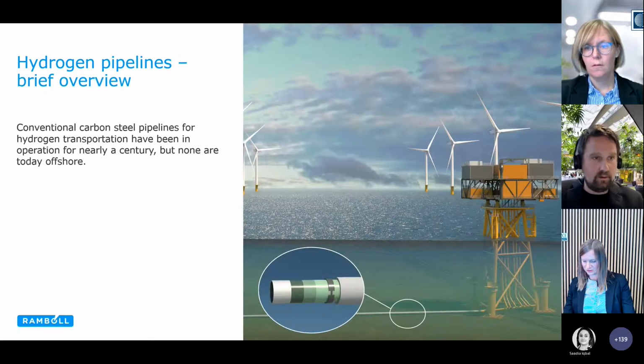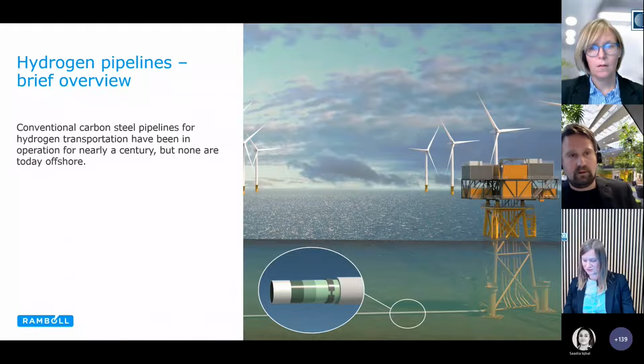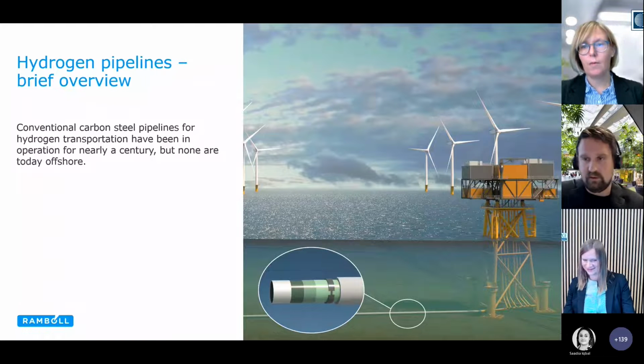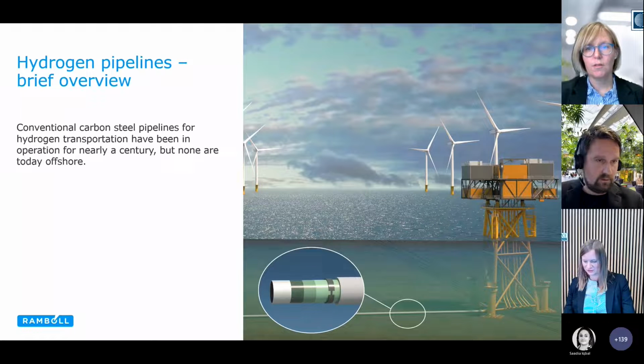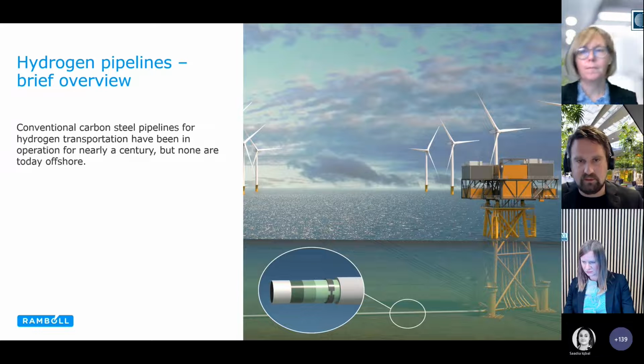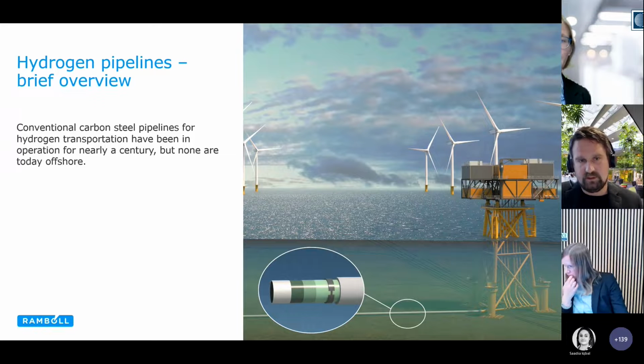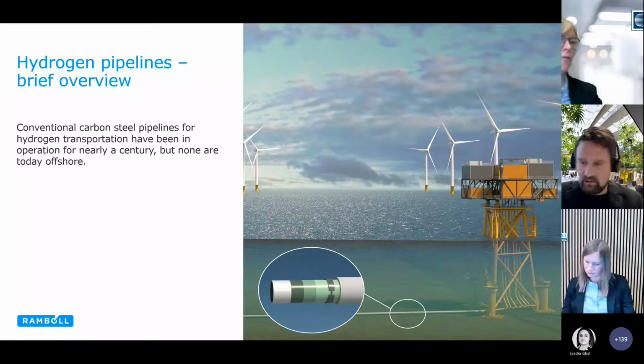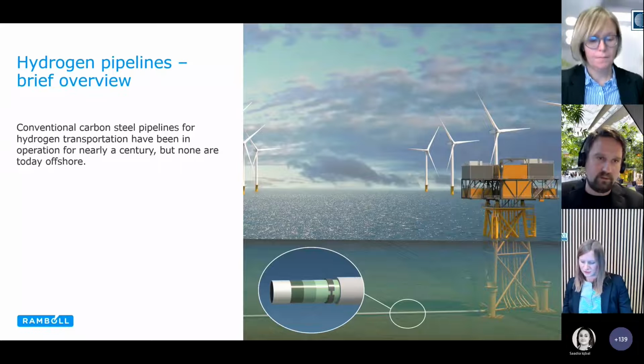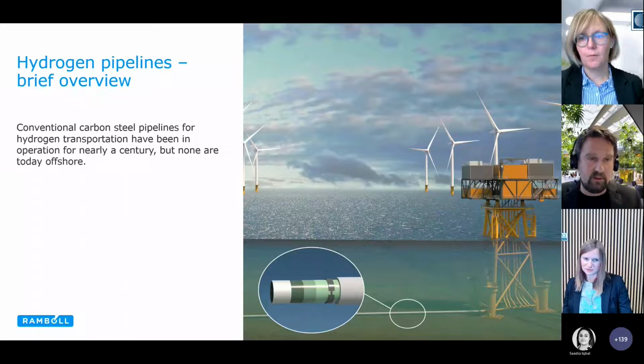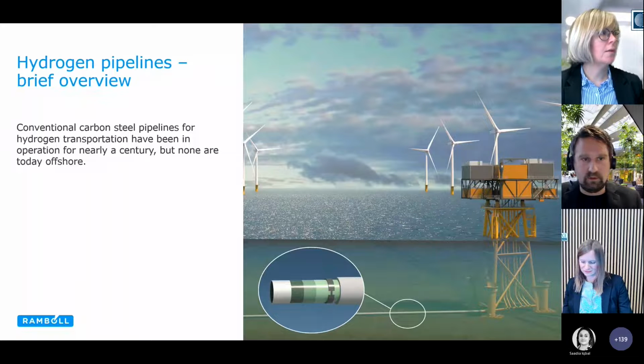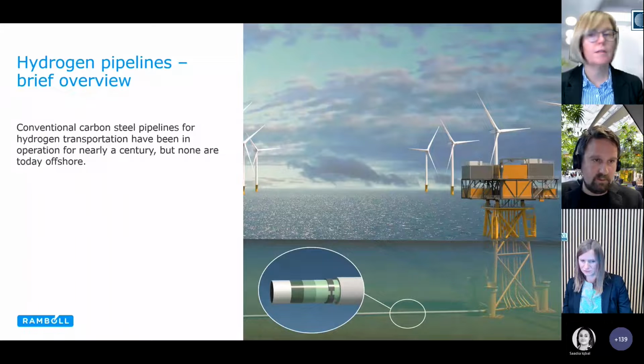A brief overview of hydrogen pipelines. Carbon steel has been used for hydrogen pipelines for almost a century, so we don't see that as a novelty per se, although they are usually with relatively soft steel compared to the modern natural gas pipelines, and shorter distances and even lower pressures. But there is a lot of knowledge in industry experience, and the ASME hydrogen pipeline code acknowledges this, that there is vast experience, but more laboratory data is needed. Hence, people like Ditte.